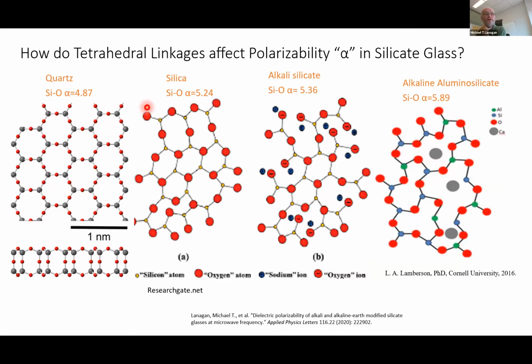As we talked about in a previous slide, the polarizability calculated we would need for amorphous silica. It's a disordered structure, a little bit extra motion in that, and we get a higher polarizability. As we start adding silicates and modifying and opening up the structure, just looking at the polarizability of this silicon oxygen tetrahedron, we can see again a slight increase. And this is all detailed in this publication here.